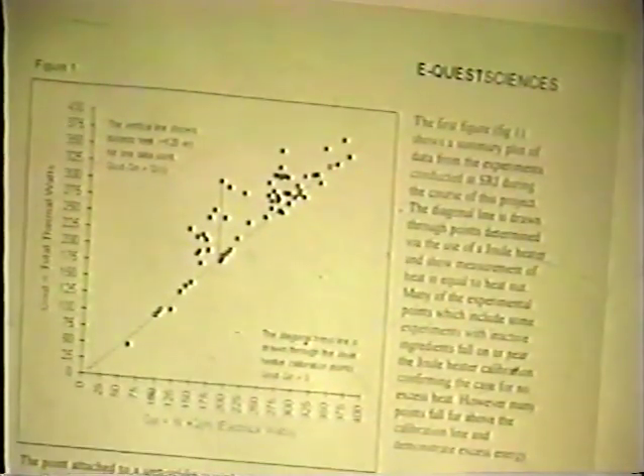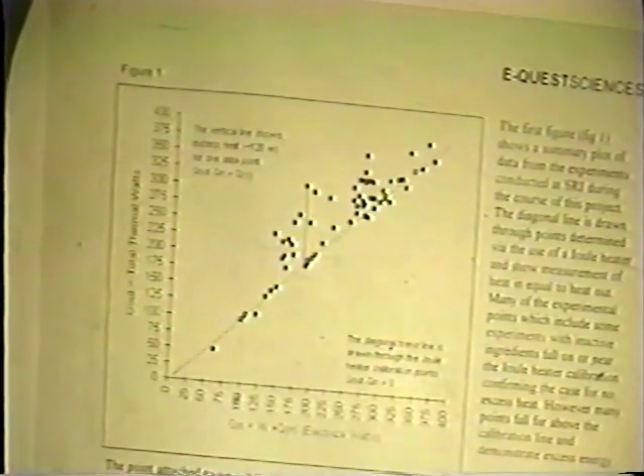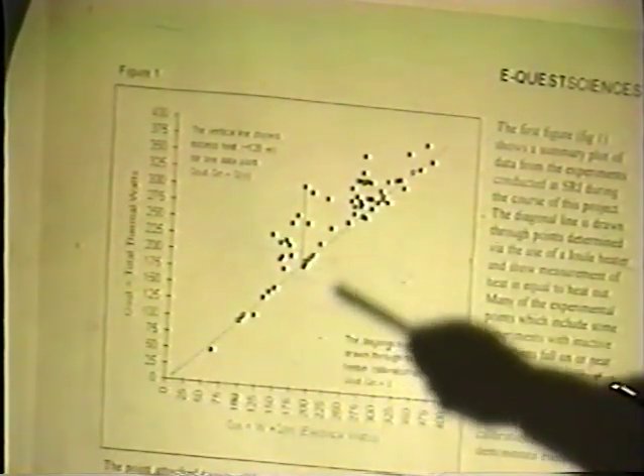When we plotted the data of all the experiments, I'm kind of hustling along to get onto the nuclear parts, but this is the data from the SRI report, which is about to be published by EPRI as an EPRI technical report. We have a line here, which is energy in equals energy out, and some of the square marks on the line are joule heater calibrations, and the rest of the spots are experiments that ran. And so in an experiment like this, where we were putting in something like 180 watts of energy into the system, we were measuring about 310 or something of that nature output.